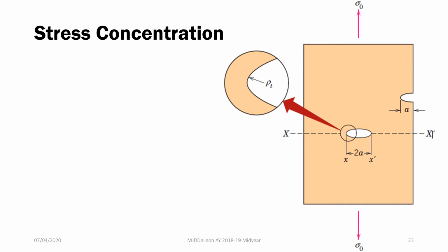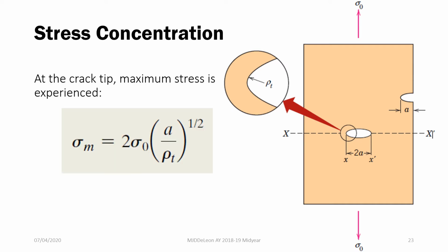So at the crack tip, we experience what we call stress concentration. The maximum stress that is experienced at this crack tip is given by the following equation. Sigma M, or the maximum stress, equals 2 times sigma naught, where sigma naught is the applied stress, times a over rho T raised to 1/2, where a is the crack length and rho T is the radius of the curvature of the tip.